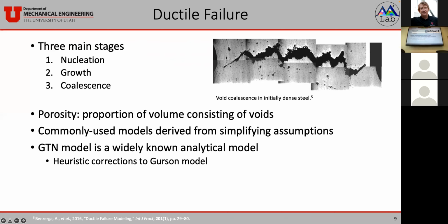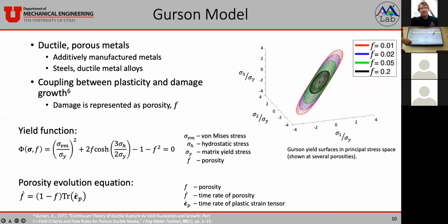A common parameter to describe damage in ductile failure is porosity. This is the proportion of the volume that consists of voids. Within ductile failure, commonly used models are derived from simplifying assumptions. These involve voids remaining spherical during the growth, which is not realistic, self-similar void growth, and so on. The most widely known model of ductile failure is perhaps the GTN model. This was developed in the late 70s, and this was an extension of the Gurson model. It applied heuristic corrections from unit cell simulations. The Gurson model only targets void growth. It has a very simple analytical form. For these reasons, we targeted the Gurson model as a ductile failure model that we will attempt to recover with GPSR.